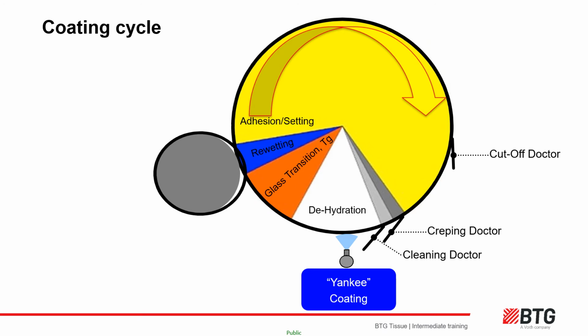You will also hear terms from suppliers such as cross-linking and pre-cross-linked and even dehydration polymers. Don't panic. Cross-linking simply means polymer chains reacting with each other to form a multi but micro-layered matrix. Traditional polyamine epichlorohydrin resins or wet strength resins cross-link, and the process is accelerated by heat, high pH and slowed by conditions of low pH, high chlorine, high oxidizers and colder conditions. This can be useful information to know. Pre-cross-linked simply means that the cross-linking reaction happens in the production plant of the chemical supplier. Products can also be partially cross-linked, which is when the cross-linking reaction is stopped by adding either caustic or acid partway through the production process. Hence, base coats can be alkaline as well as acidic.